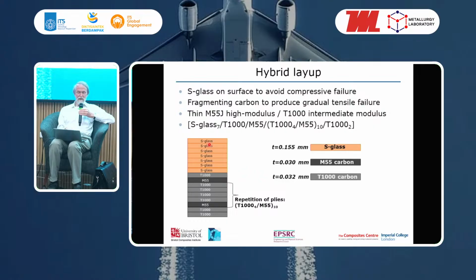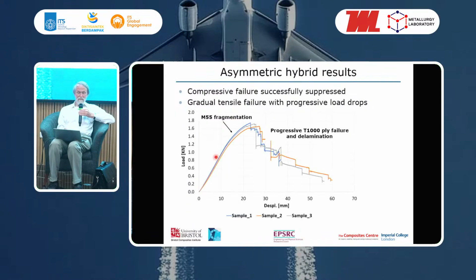So to do that, we had a block of S-glass. This is unidirectional material, a block of S-glass, and then this carbon hybrid, where we're hybridizing T1000 intermediate modulus with a high modulus M55 all the way through the thickness there. And these are all thin plies with a standard S-glass on the compression surface. And when we tested these, it behaved very well.